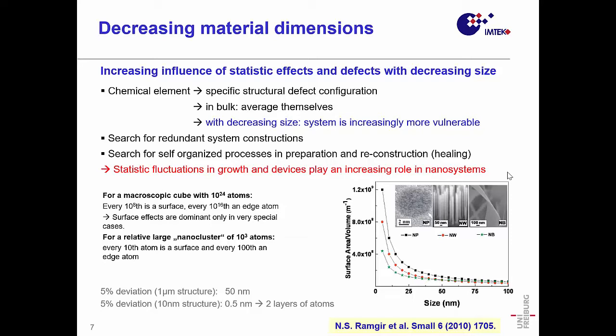We calculated the surface to volume ratio for different kinds of objects like quantum dots or nanoparticles, nanowires, and nanobelts. And what you see is, if you stay above 100 nanometers, everything is okay. If you go to 50 nanometers, you already have an increase of the surface ratio. If you go below 20 nanometers, then the surface might take over. What you have there is an increasing effect of statistics. You have an increasing possibility of defects which affect what you're doing.